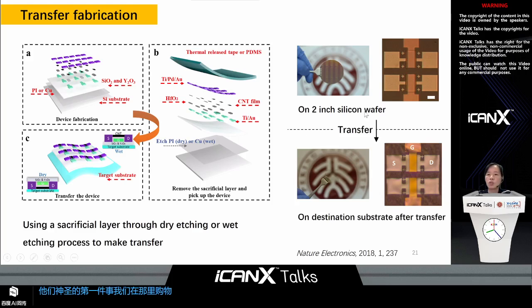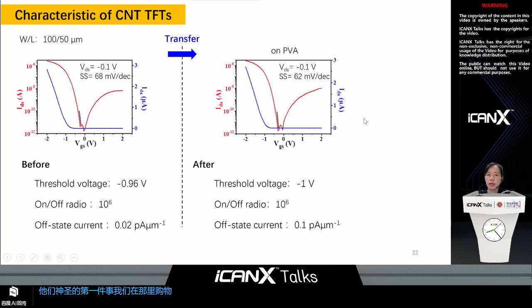And this fabrication can be done on a 2-inch silicon wafer. During this transfer process, we checked the device before and after transfer. Here the 2 curves show that they are almost the same. So that means the transfer process itself has a very minimal effect on the device performance.